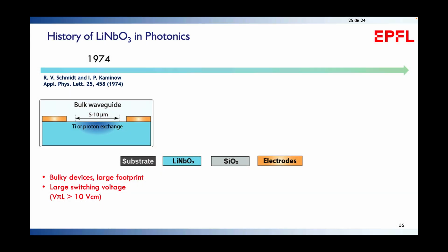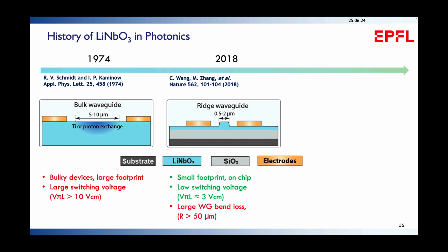And so over the last decades, there's been really tremendous interest in lithium niobate. Lithium niobate was once hailed as the silicon of photonics. It was studied extensively in the 70s for its ability to make optical modulators using a process called proton exchange. So you can diffuse protons, or titanium, inside lithium niobate to make bulk optical waveguides. And a seminal turning point was about 2018. That turning point was triggered by the availability of thin film lithium niobate on insulator.